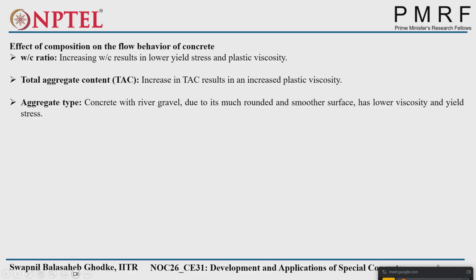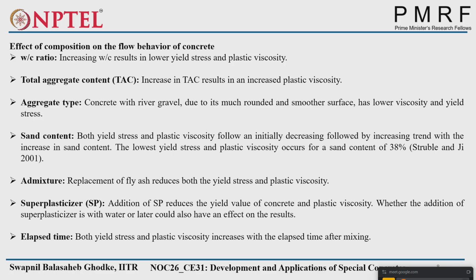Rounded particles flow easily, as they have less internal friction. That's why there is lower viscosity and yield stress with river gravel and rounded, smoother surface particles. Sand content: both yield stress and plastic viscosity follow an initially decreasing, followed by increasing trend with increasing sand content. The lowest yield stress and plastic viscosity occur at a sand content of 38%.